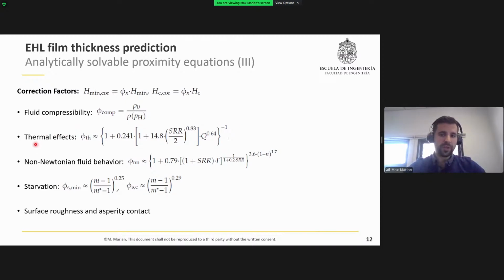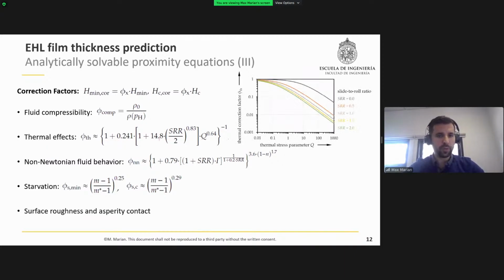The deduction of non-dimensional parameters in the film thickness equations was also based on isothermal considerations. However, if we have high speeds, high velocity differences, or high slip of the rubbing surfaces, there might be some local temperature that exceeds the bulk temperature of the contacting bodies, and also influence basically the viscosity of the lubricant, and thus also the film thickness. So for example, Murch and Wilson introduced the so-called thermal stress parameter Q, which also includes the viscosity temperature coefficient, to determine the thermal film thickness reduction, which was later extended to also cover the slide to roll ratio as SRR. So here, basically, we can see the thermal correction factor versus the thermal stress parameter and dependency of the slide to roll ratio.